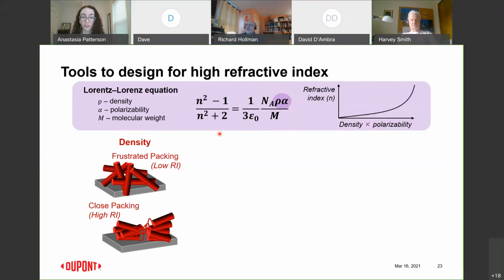So density kind of makes sense intuitively. If you have a very frustrated packing or a lot of void space in your material, you're basically averaging in a lot of air or vacuum into the pathway of light. And that's going to reduce the refractive index towards something like air with very low density. So for example, if we use the covalent organic frameworks from the gas sensor project in an optical film, it'd probably be very, very low refractive index because there's so much void space in those materials. And of course, the opposite is true. If you have very close packing or high density, then you get high refractive index. And that's something you can imagine sort of like a diamond. That's very high refractive index.